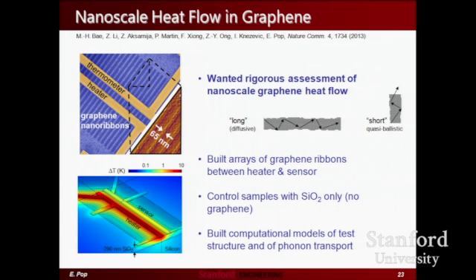So we built these test structures as arrays of graphene nanoribbons, and this is the simulation of the structure. This is the actual experimental picture. And this is sort of the idea that we formed, both before and after our measurements. Basically, when we have long and narrow graphene ribbons, you have a lot of scattering, and you're essentially in what's called a diffusive transport regime. If you make really short graphene nanoribbons, even shorter than a quarter micron is fine, you're in what's called a quasi-ballistic regime, or you're approaching this ballistic quantized conductance regime that had been theoretically predicted but never measured at room temperature.